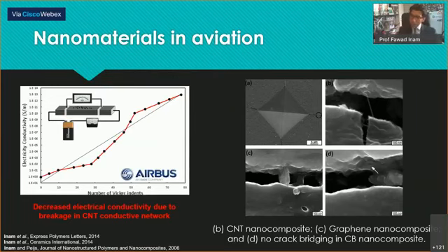So what we were suggesting at the time is that you could actually put nanomaterials. You can see here, this is just an example where we were looking at the mechanical performance, and what we also realized is that by replacing copper with carbon nanotube and/or graphene, you're also making the product a bit smart.